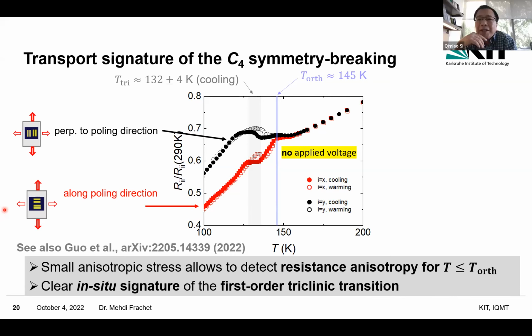So in principle, yes. I think one of the messages is that there is a very large fluctuation regime above all this transition, especially above the orthorhombic transition. The behavior of the lattice constant along the c-axis and along the a-axis is really anomalous, which probably comes from some kind of fluctuation regime that already starts at room temperature. You already have this transverse optical phonon softening, which occurs at very high temperature, up to room temperature actually. So it's a very gradual change. Thank you, KP.